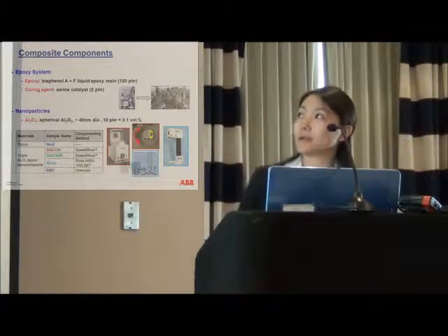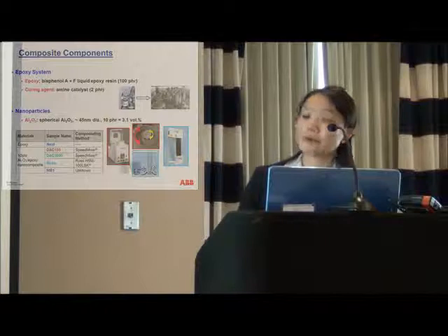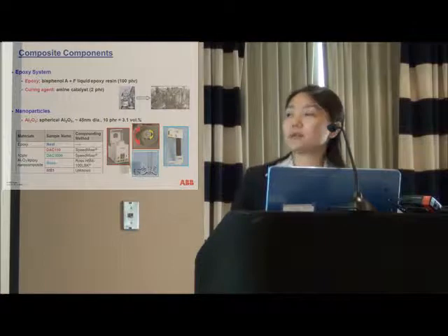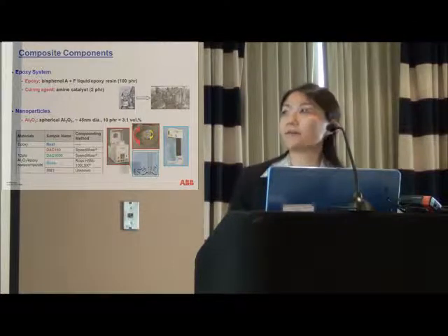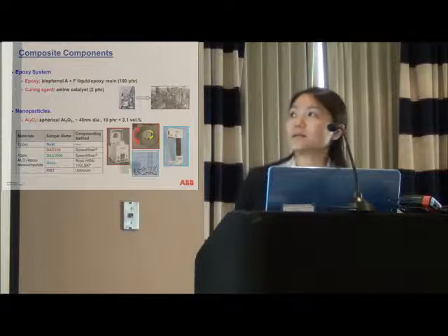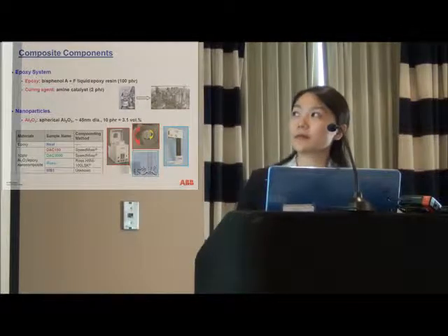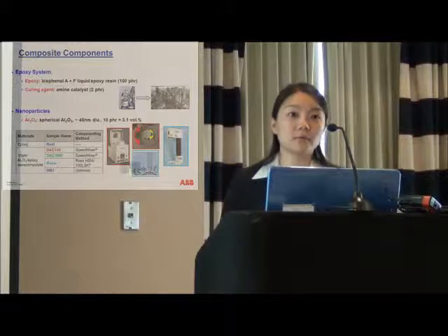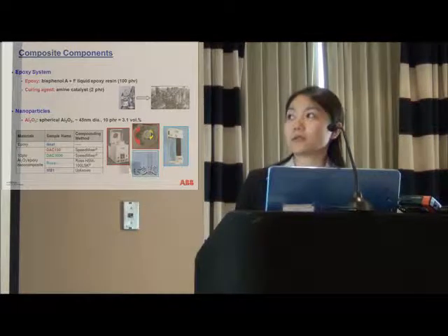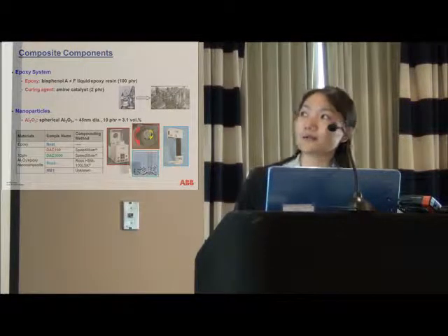So this is about this paper. We were trying to upscale this material from lab scale to at least about 5 liters. The epoxy system here we used was a very simple one - bisphenol A plus bisphenol F liquid epoxy, and the curing agent was an amine catalyst.